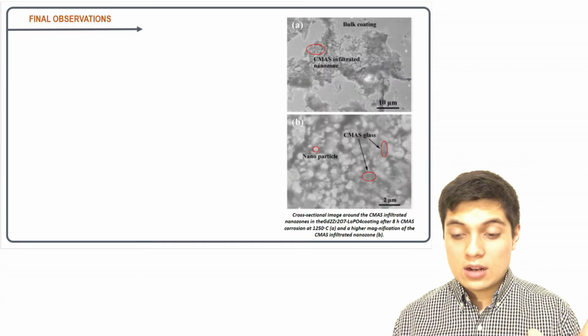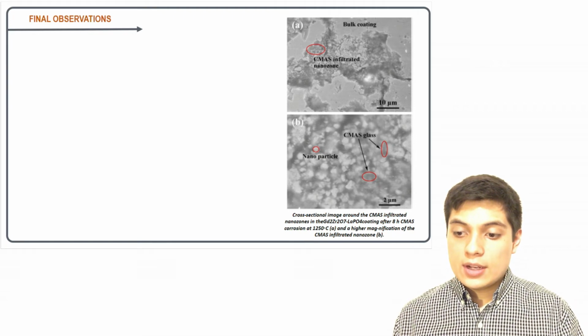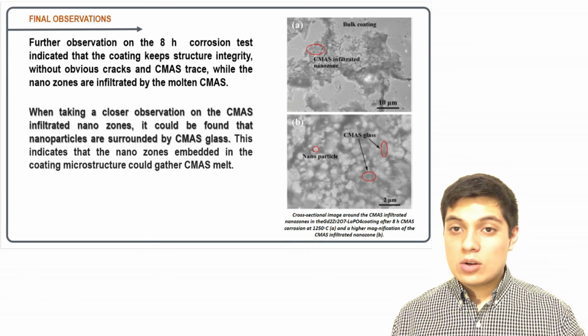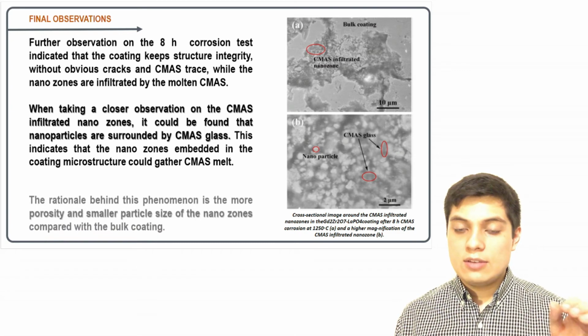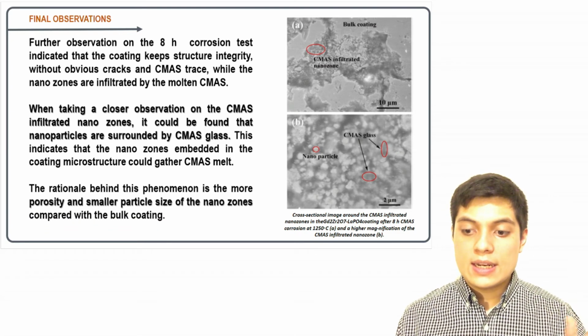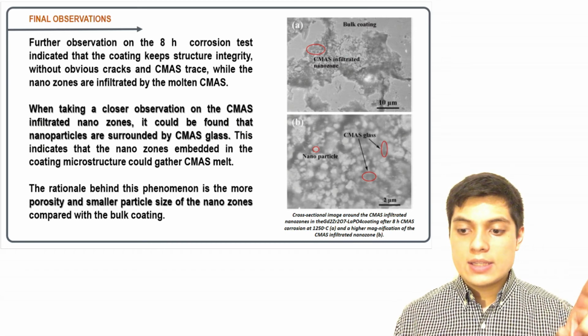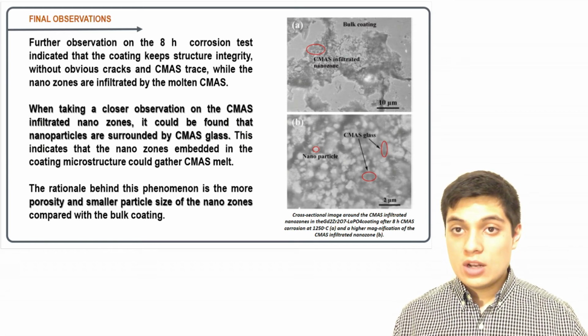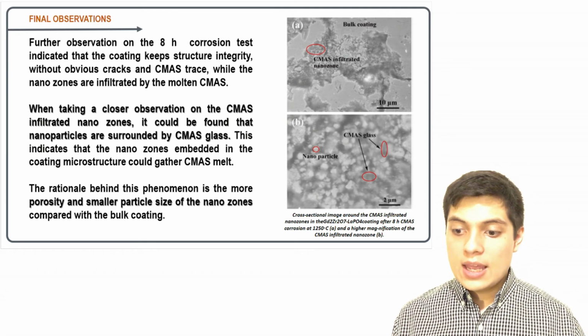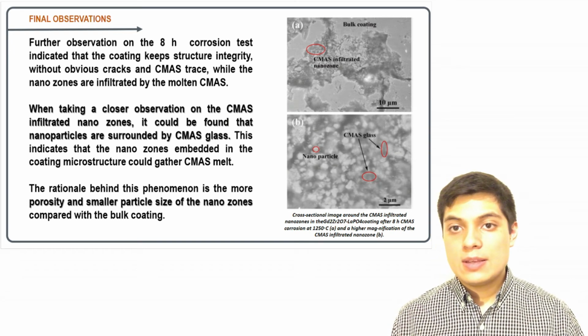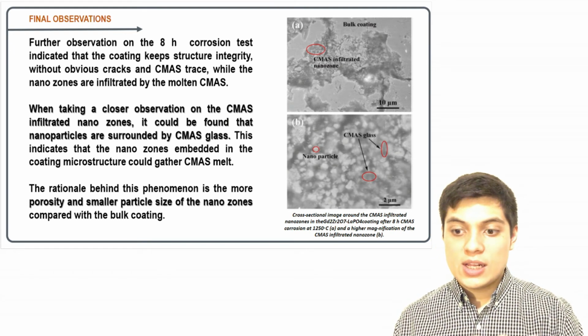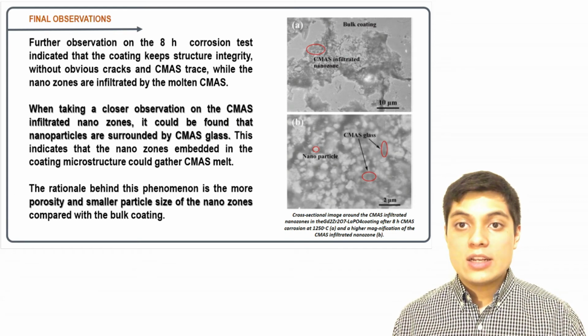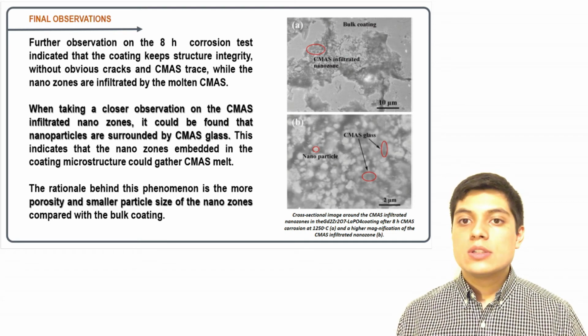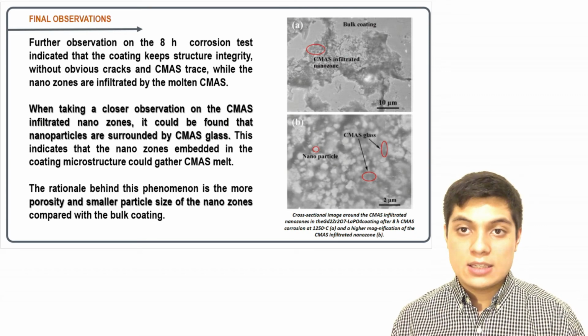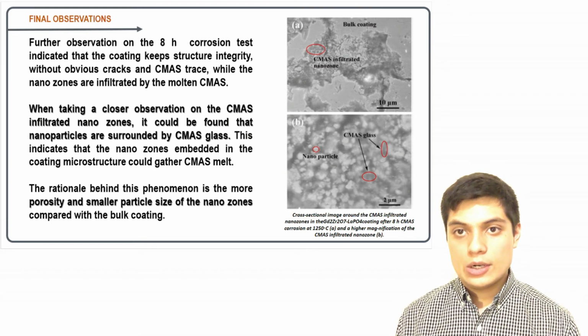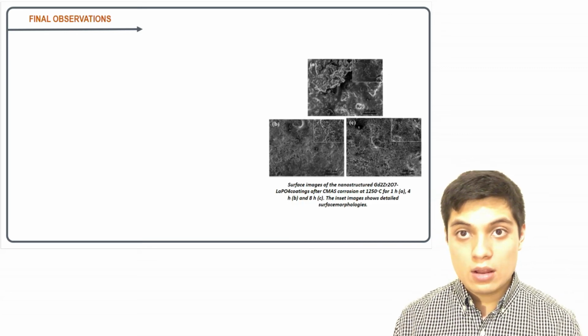And here are some final observations. When taking a closer look at the CMAS infiltrated nanozones, it could be found that the nanoparticles are surrounded by CMAS glass. The rationale behind these surrounding particles is that the nanozones, or the lanthanum phosphate materials, have more porosity and a smaller particle size, which causes them to gather more CMAS. But this is not something bad. We're going to see the other final observations.